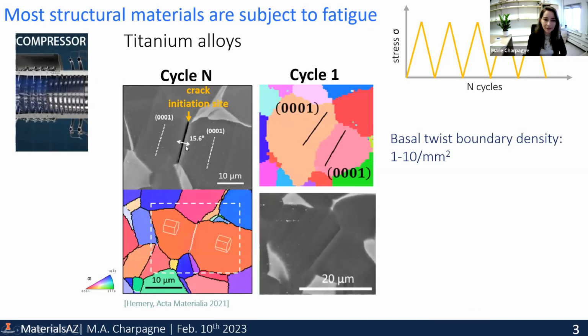And when we look at, again, these initiation sites, we again find in pretty much all titanium alloys, in recent work where we highlighted this, that the initiation sites also correspond with crystallographic facets. So this is an HCP material, and of course the crystallographic facets are very different. Here we're looking at twist boundaries between the basal planes, between two HCP crystals. And that's after many cycles, right? You don't have a crack in the first cycle, thankfully. But when we look at what happens in the very first loading cycle, we see the development of what we call a slip band.